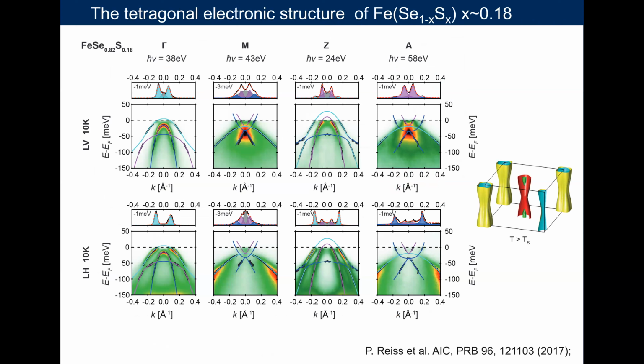The tetragonal Fermi surface of these materials is surprisingly very similar to what we see in iron selenide in the tetragonal phase. So that's why this isoelectronic substitution is quite beautiful, because we can recover the tetragonal phase we started with at high temperature. And sulfur substitution is a very, very clean tuning parameter.